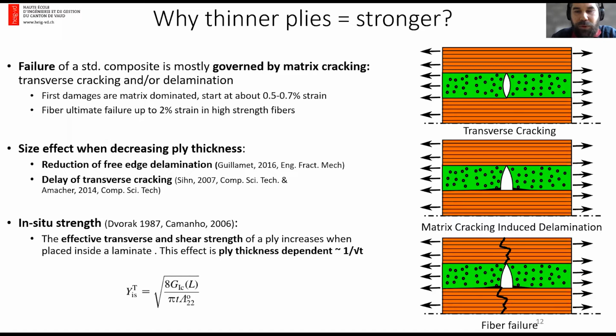However, when you look at the on-axis plies, we can use fibers that have an elongation up to 2% strain. So this means that a composite is only safe to be used for a fraction of the maximum strain of the fibers that are used. And that's a pity because we are paying a high cost for high performance fibers, but we are only using about 1/3 of this range of loading that we could use normally.